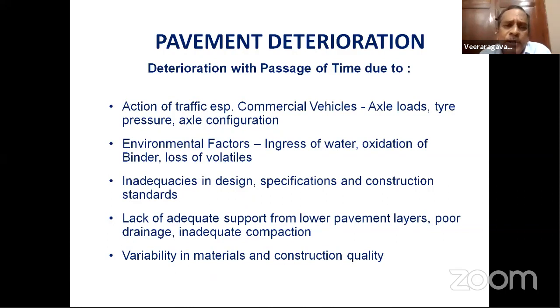So whatever you decide, the pavement will deteriorate with the passage of time, mainly due to wear and tear, due to fatigue, because of the heavy commercial vehicles. Secondly, when they are exposed to the environment, there may be some top-down cracking. Once the crack starts, unless you seal it with an emulsion, water will enter, ingress of water. Because of oxidation of the binder, the surface is likely to crack. Once the water enters, potholes form. And that is again a cause of delayed maintenance action, but the pavement will eventually deteriorate.